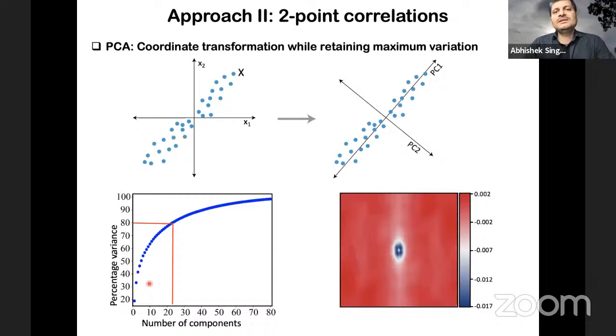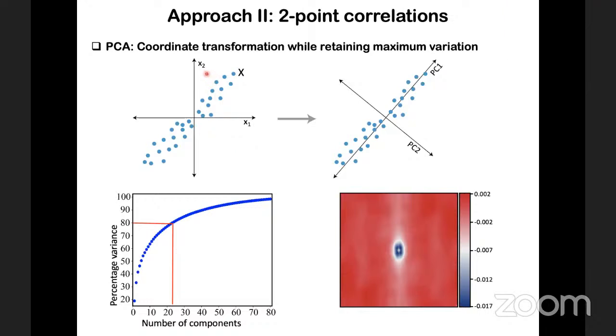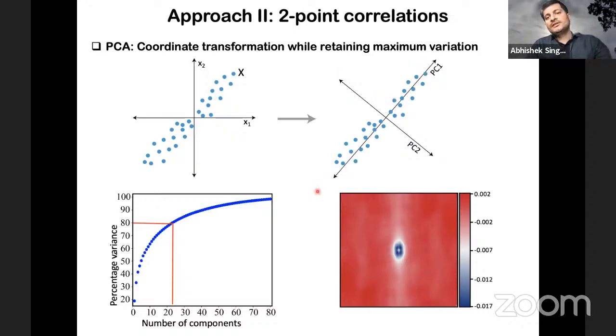So what we do is use PCA, or principal component analysis, which is essentially a coordinate transformation, and tells you the coordinate directions which have the maximum variability. For example, this was x1, x2. You rotate it and put your axis in this direction. You see PC1 covers most of the variation, and PC2 covers whatever is left, which is a little bit. So two principal components were good enough to capture most of the variability in the data. This is what we found in our data also. Of course, in our case, we needed about 25 PCs to capture almost 80% of the variance. So we stop at that point.